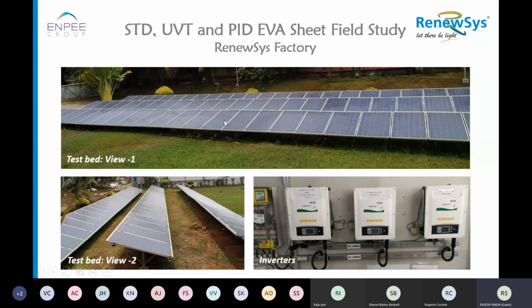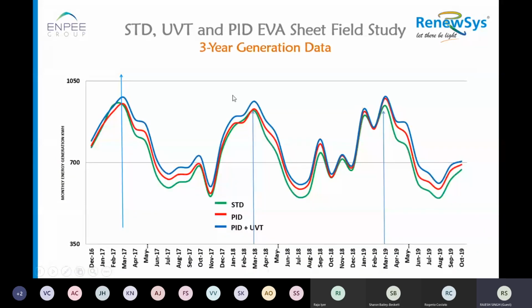We have done one interesting study in our company where we installed module demo plants of 6 kilowatt each using standard EVA, ultraviolet EVA and PID EVA, and we compared the data of the last 3 years. We found that whatever is talked about theoretically, practically we are getting the same result. A few conclusions which can be drawn are that the PID and UVT combination gives the highest power in all the seasons, followed by PID, and the least power generation happens in standard EVA.